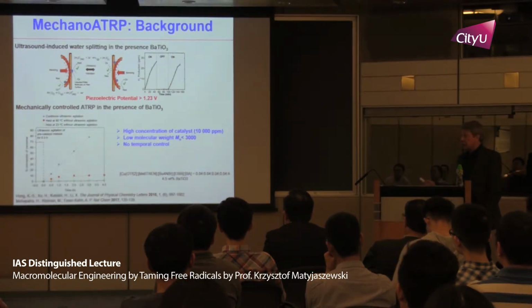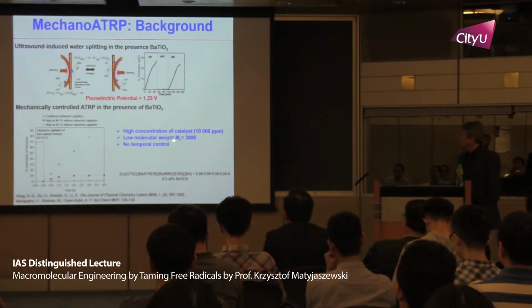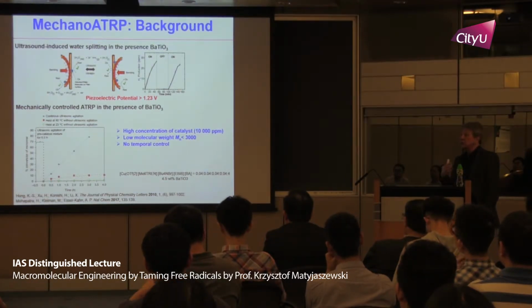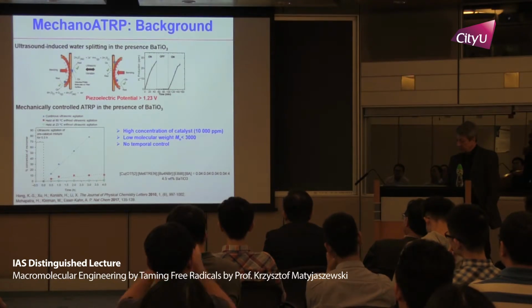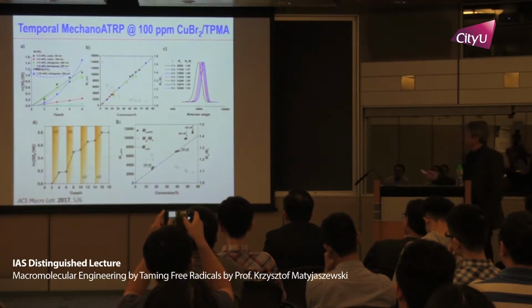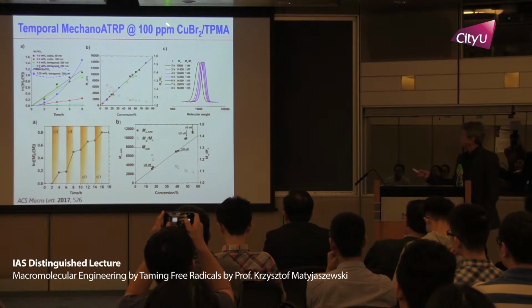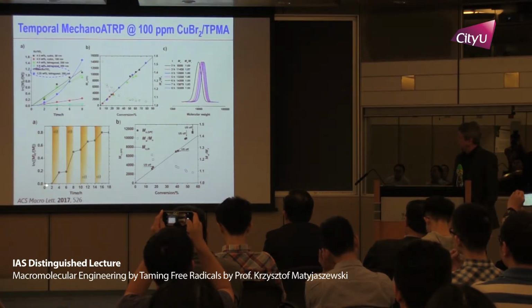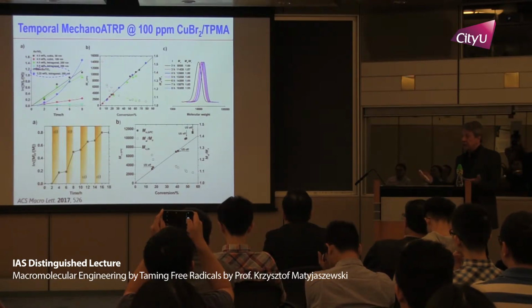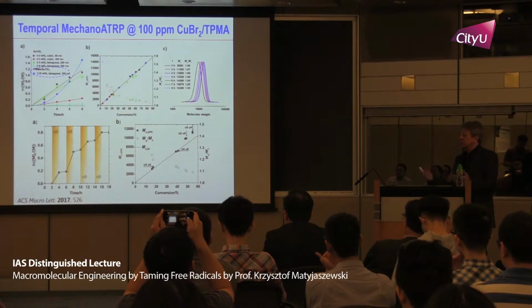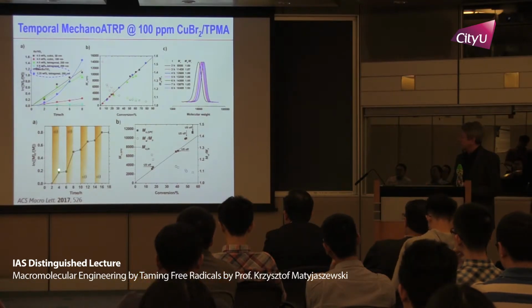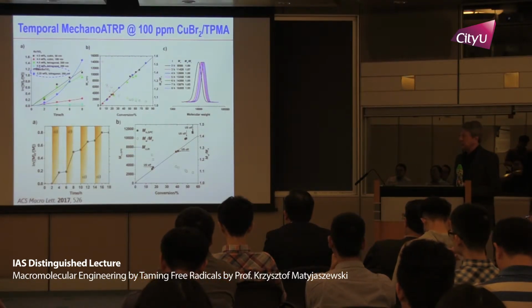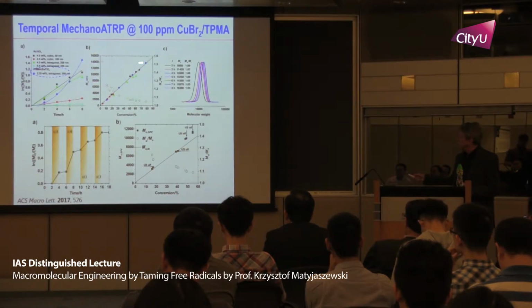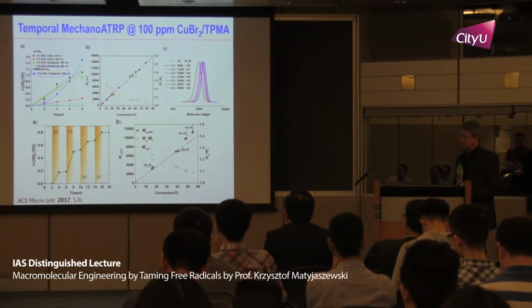And it worked, but on the low molar masses, no temporal control, because it was so much catalyst, you couldn't stop it. So what we did, in fact, we reduced the amount of copper to 100 parts per million, and you could see that in that case, you apply ultrasound, it goes, you switch off, radicals terminate, copper 1 gets oxidized to copper 2, it stops, and then on-off reaction. Good control of molar masses, low dispersity.